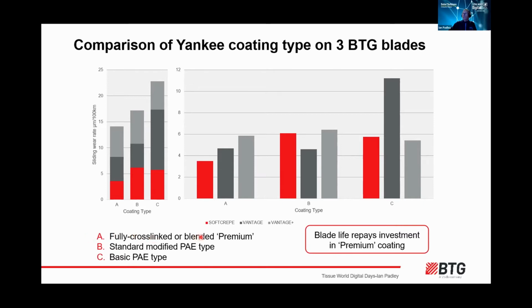The fully cross-linked or blended premium type coating. You may hear words like hyper-branched or, what we say, thermoplastic coatings applied to these. The standard modified polyamide epichlorohydrin, PAE type, and the basic PAE type coatings, which are unmodified wet strength resin. Again, we've got the 3 blade types, and it's probably more clear on this one, doing a cumulative effect of all the 3 coating types and all the 3 blade types, that the A type, fully cross-linked or premium type coating, all other things being equal, is giving a lower wear rate.